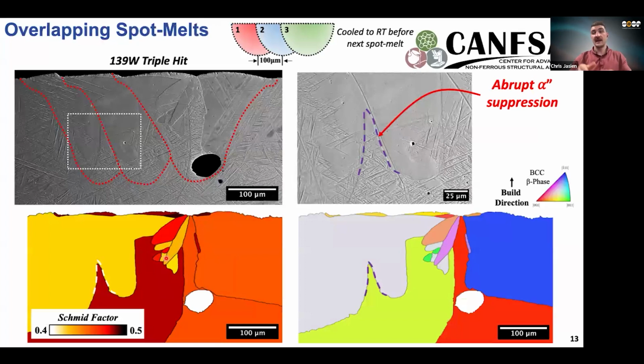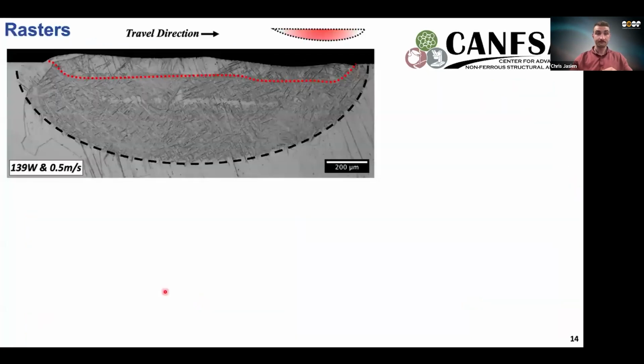So on the left here is a populated Schmid factor map, where the darker colors are the higher Schmid factors. And so what we see is that this grain that showed significant amounts of transformation indeed did have a higher Schmid factor. So that justifies to us that, okay, this is actually affecting what's going on.